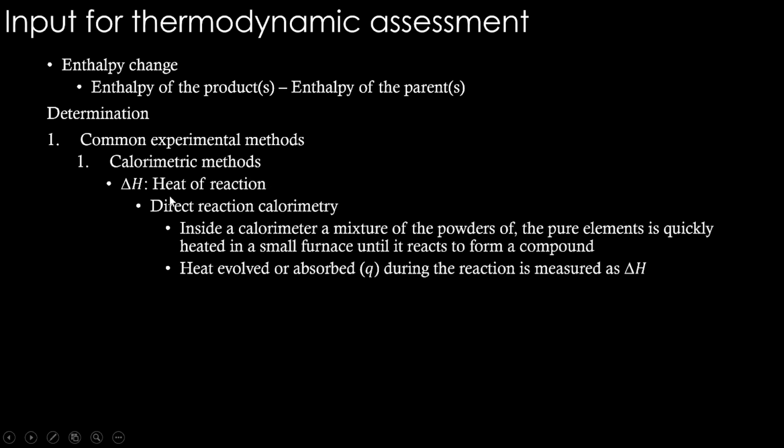Then there is heat of reaction, which can be measured using direct reaction calorimetry. Here, inside a calorimeter, a mixture of powders of the pure elements is quickly heated in a small furnace until it reacts to form a compound. When the compound forms, the heat evolved or absorbed during the reaction is measured as delta H. That is heat of reaction, or enthalpy of reaction. Okay.